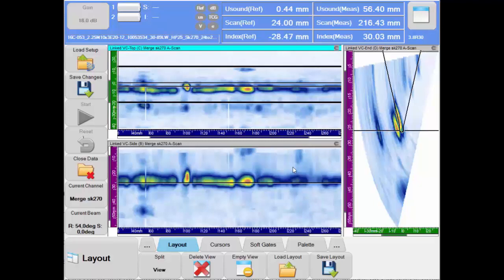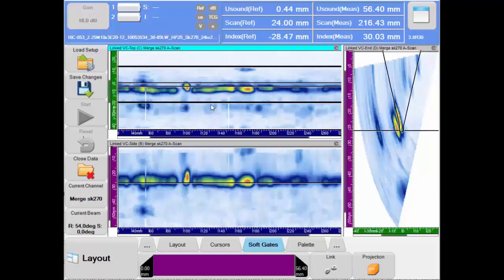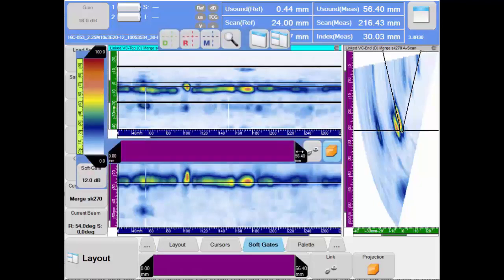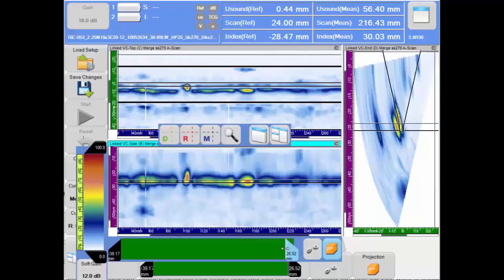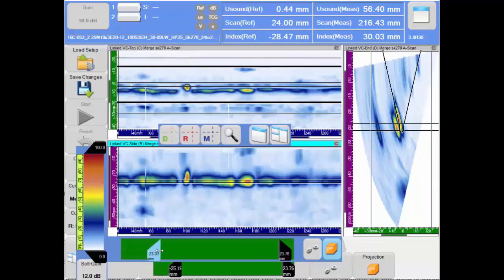Data acquisition was performed at low gain setting to avoid saturation on flaws with high reflectivity. The 16-bit data resolution allows us to use appropriate soft gain settings for each defect type. The projection gates can be positioned to facilitate data interpretation, for instance, by hiding the strong root signal on the top view and by eliminating the shear wave mode conversions on the side view.